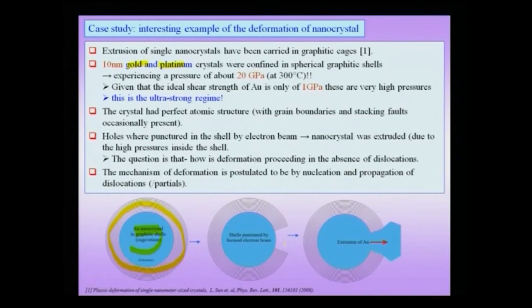This is punctured by a focused electron beam, the shells are punctured, then this is extruded using this nano cage. Now, this is like a nano extrusion cell. So, you have a carbon onion which is punctured, and this gold actually is extruded like you would do a bulk extrusion from this carbon onion cage, and this extrusion has been studied.